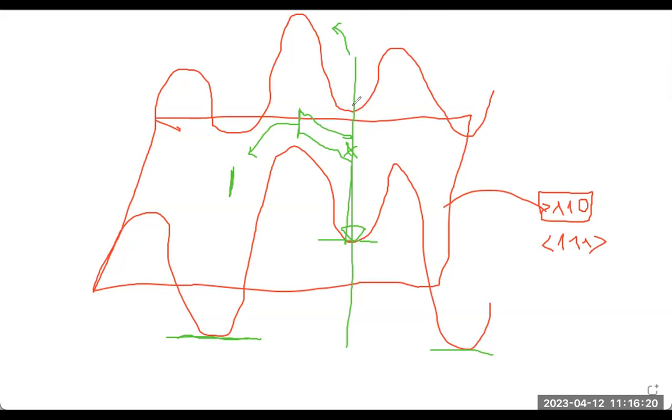Then the rest will start to evolve at the higher energy level. Then they move to other energy states. Then we kind of create the kink formation. So these are just edge parts of the screw dislocation. Then this is the screw part again.